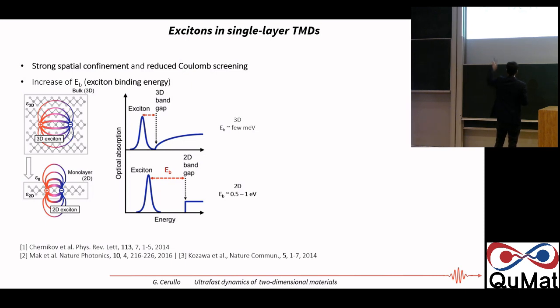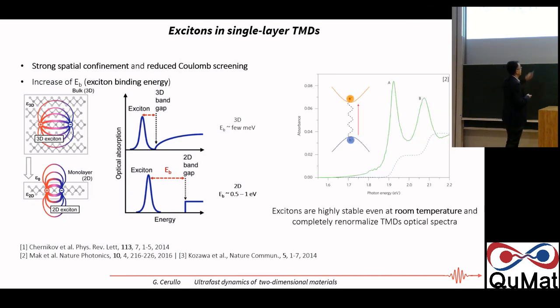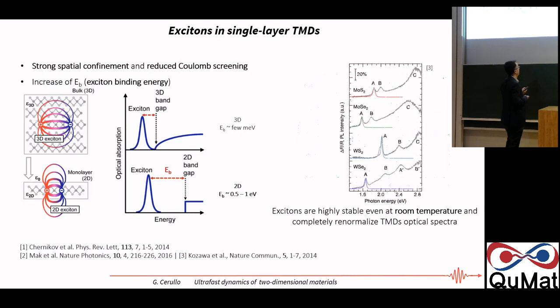So the screening is also strongly reduced. The combination of confinement and reduced screening dramatically increases the binding energy of the exciton, which now becomes a fraction of an electron volt. So you really have binding energies of maybe 0.2, 0.3, 0.5 eV, which are, even at room temperature, the excitons are very clearly visible and dominate the optical properties of these materials. And in fact, you can see them very clearly, even in room temperature conditions.